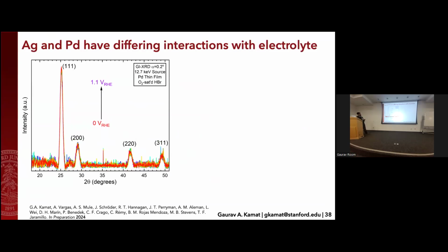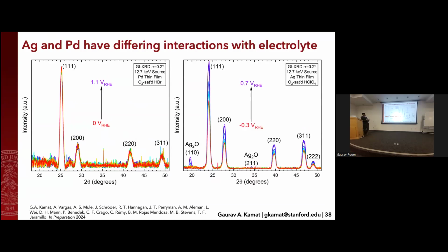Now, unfortunately, on palladium, when we did this measurement from 0 to 1.1 volts, we didn't really see a lot of changes in the crystalline structure. But when we did this on silver, we saw quite a few changes. So one, you see that these peaks are sort of getting higher in their intensity. Again, everything has been calibrated in reference to the incoming intensity. And so this means that your system is getting more and more crystalline sort of as you apply higher potentials.